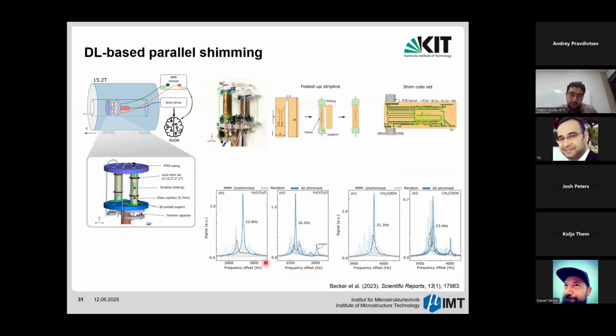As you can see, here are examples of how this model works. Again, it starts from the unshimmed spectrum and then does seven random shimming steps, and after that, it immediately predicts the final shims, which is more or less similar to what we could achieve manually. Unfortunately, there exist no optimization algorithms for such an experiment. It's completely new. We have a parallel setup, and we don't have on the machine an optimization algorithm that can shim this.